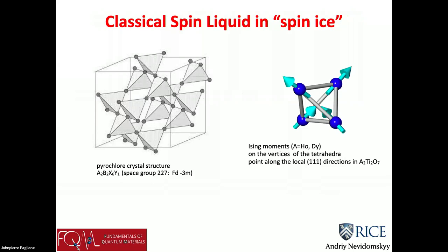But what it has is a bunch of corner-sharing tetrahedra as shown in this picture here. And on each tetrahedron, you have moments that have strong Ising anisotropy. That's because there is a strong spin-orbit coupling. The moments on holmium or dysprosium are huge. We're talking about spin S, which is 15/2 or 8. So it's a large spin. And this large spin tends to point along the local 1-1-1 direction. But the 1-1-1 direction is not the global one; it depends on which corner of the tetrahedron. So on each site of this tetrahedron, it's a separate local direction.